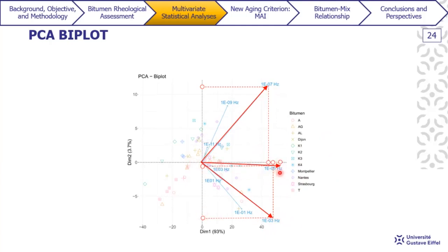Whereas 10 to the power of minus 3 seems to be practically overlapped on PC1 and has almost no contribution to PC2. So we can also note that all these arrows are pointing toward the right, which means that if you had an increase in any of our phase angle values at any of the corresponding frequencies, our bitumen would move toward the direction pointed by these arrows. But since we observe that with aging we have this overall flattening of the curve, all the values that were used in this case reduced, which is why all the bitumens with aging moved from right to the left. So here is just to try to better understand the inflection trend that we observed in this analysis.